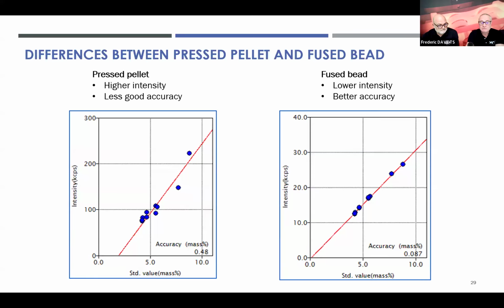But as I mentioned, calibration curves, because of grain size effects and especially mineralogical effects, are not that good anymore, especially for, let's say, the lighter elements, the oxides, sodium to calcium oxide, basically. For fused beads, we have better calibration curves for those elements.